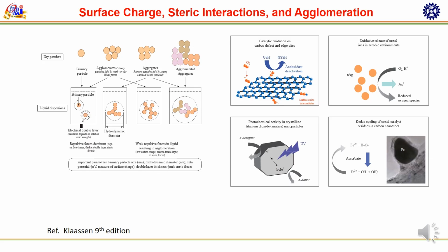Zeta potential is a measure of surface charge. High zeta potential means stronger repulsion between the particles and a stable suspension. Low zeta potential means weak repulsion and agglomeration. Hydrodynamic diameter describes the effective size of the particle in suspension, including the solution layer, not just the core. Steric forces can stabilize particles by preventing close contact. Primary particle size, hydrodynamic parameters, zeta potential, double layer thickness, and steric stabilization determine nanoparticle stability and toxicity.